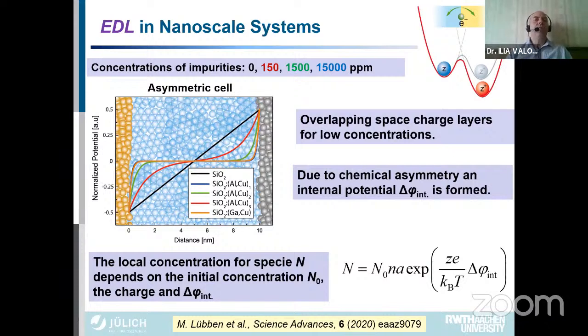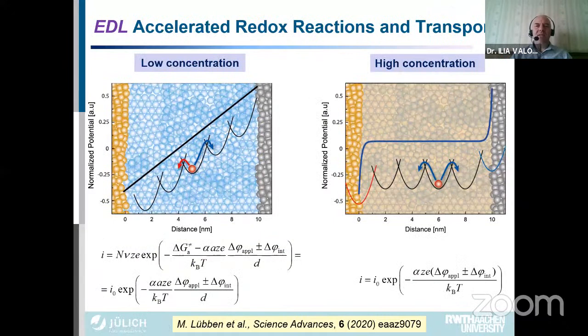And in addition to this, you see here that the electrodes are different. They have chemical asymmetry, which is intrinsically incorporated in the cell. You have internal voltage, which is formed and which drives ions to move in one or other direction until it reaches steady state. And what is the difference between these two situations when you have a low concentration of mobile species and high concentration of mobile species? So when we have a low concentration, we have a field accelerated kinetics. This means that the electric field is directly influencing the transport process, and it's much faster.